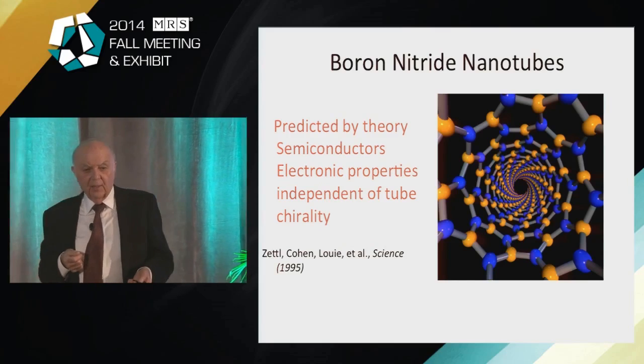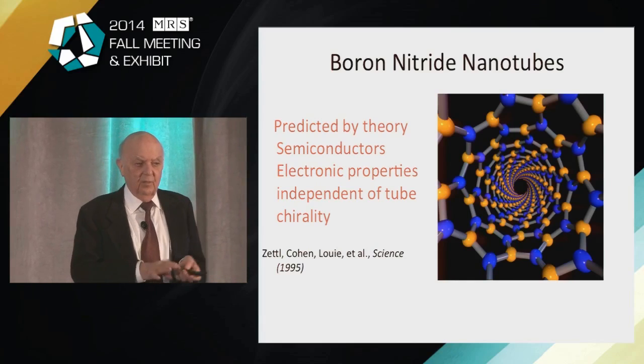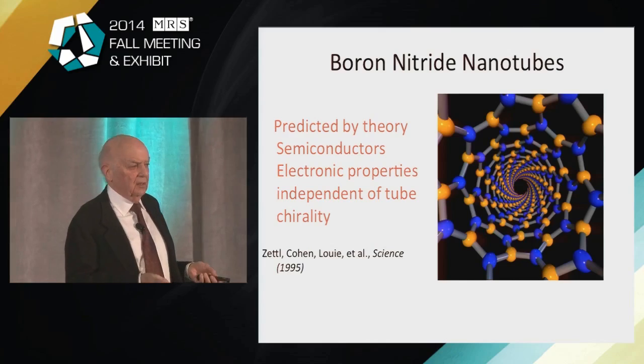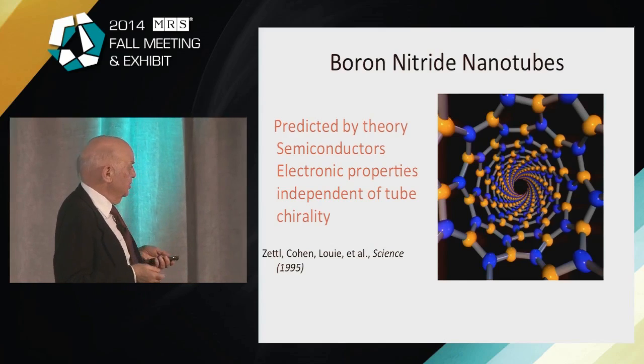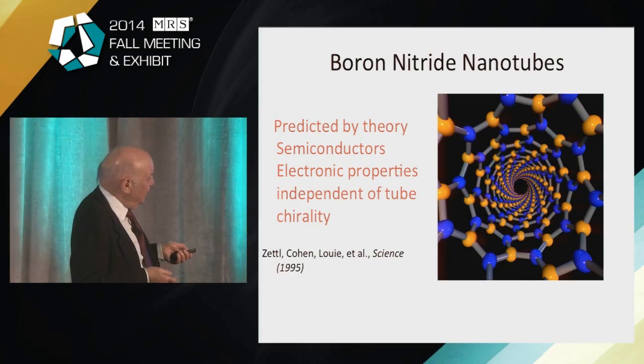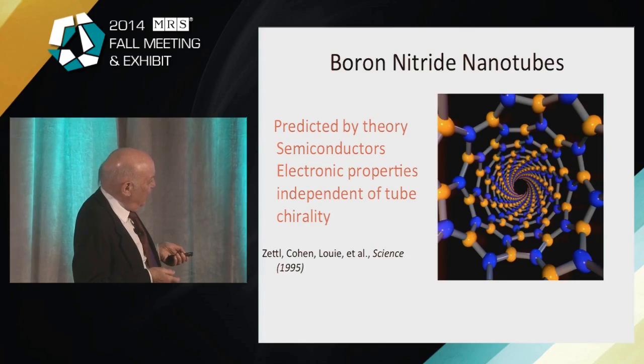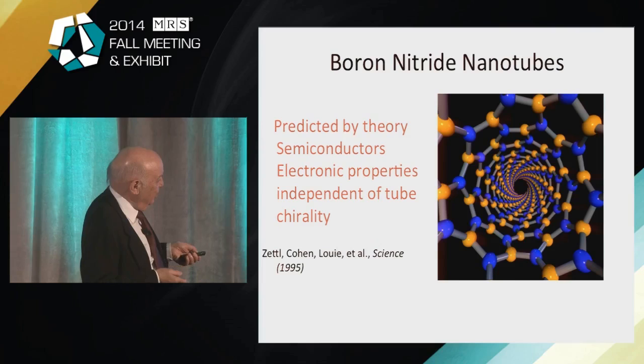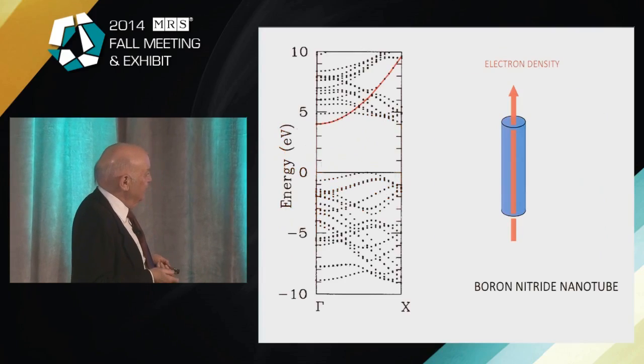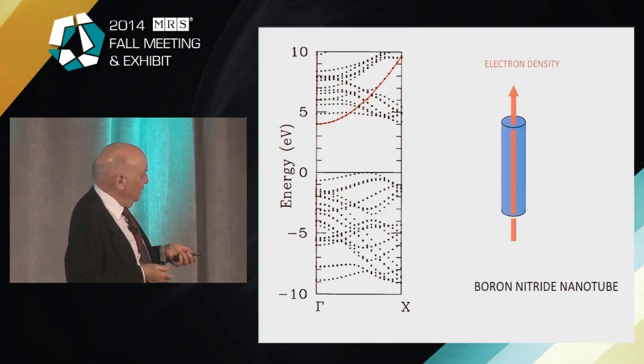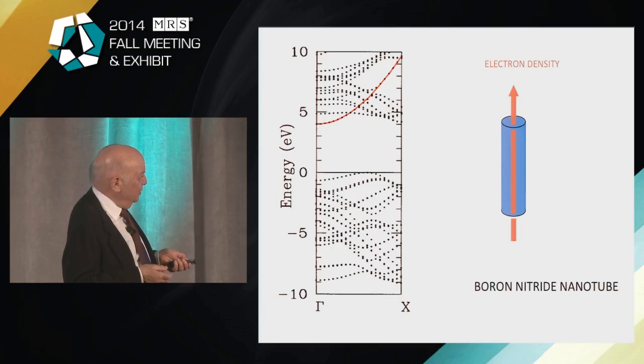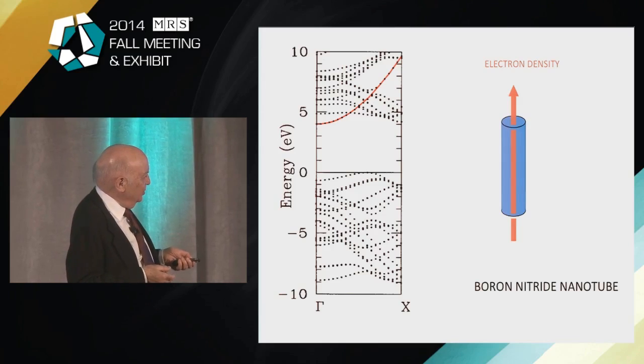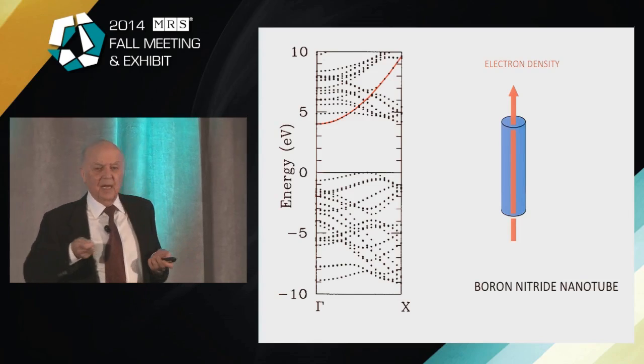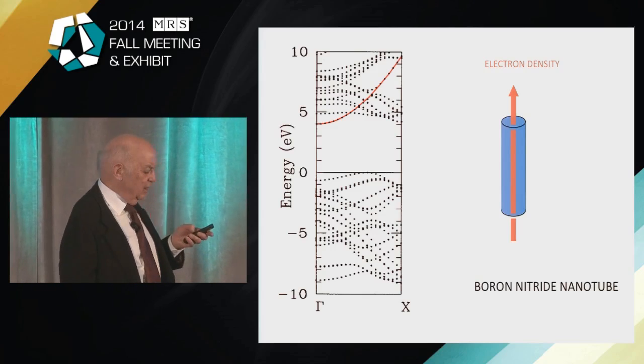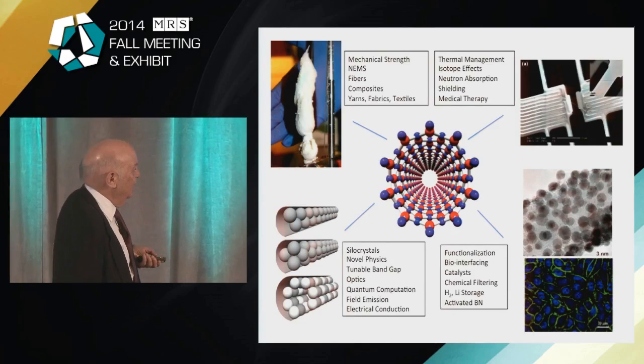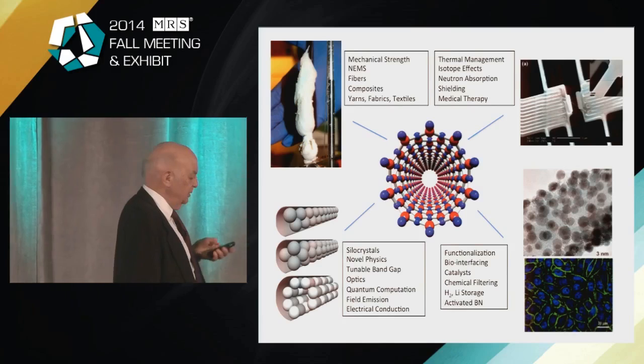Now, unlike the carbon nanotubes, which sometimes are semiconductors, sometimes are metals, boron nitride nanotubes are always semiconducting, but with a wide band gap of the order of 5 volts or so. So the different boron nitride nanotubes are like the carbon nanotubes, except you have boron, nitrogen, all the way down. And they have unusual properties. For example, if I take a boron nitride nanotube, this is the band structure, and I dope it so that it's N-type, the charge goes right up the center of the tube. So it's like a pipe for electrons. And I won't go into all the details, but the point is that boron nitride nanotubes have many applications.